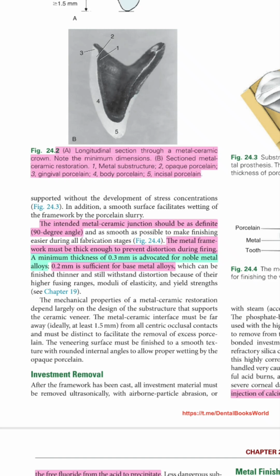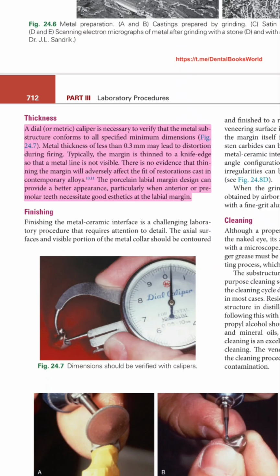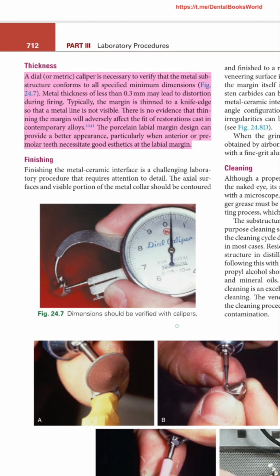far from the occlusal contacts of the opposing teeth to prevent any failure during function. The minimum thickness of the metal must be preserved during manufacturing. Less than 0.3 millimeter will lead to distortion during the firing, and it can be measured using a caliper. The margin is usually knife-edged, so the metal is not visible.